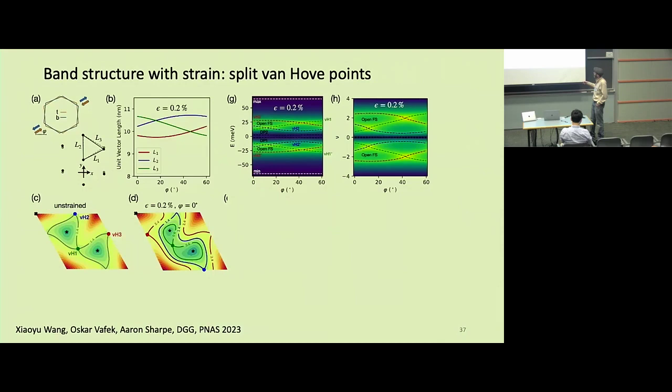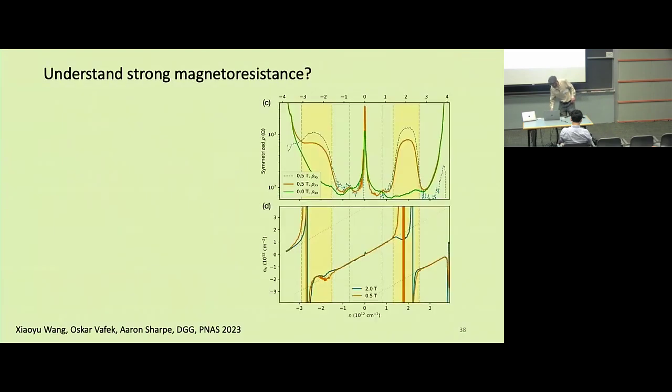That's the first of them. And then the second of those is when you again reclose into a new closed Fermi surface. So that's 2 of the Van Hove singularities, and those bound the region where we have strong magnetoresistance.